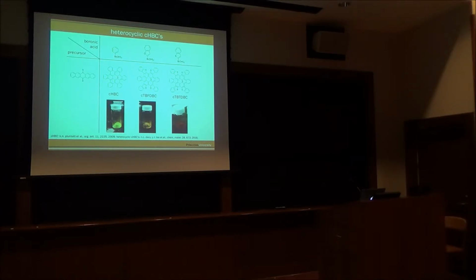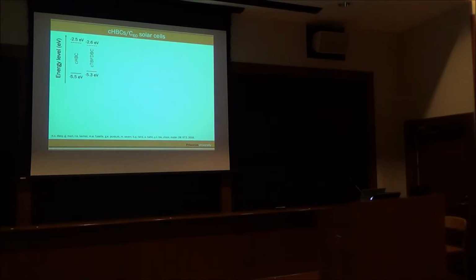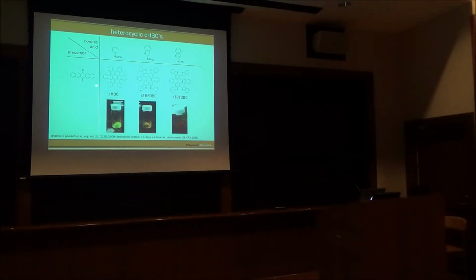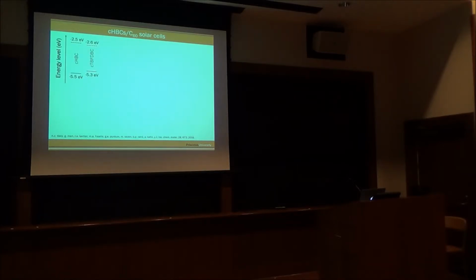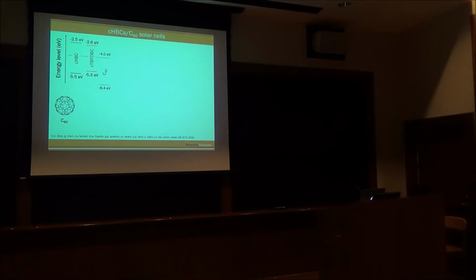So now that we have this, we can make a solar cell. These are the energy levels associated with these compounds. So this is the parent compound, CHBC. And then I'm going to show you work that's done on this benzofuran compound with the oxygen group. So this is the HOMO and the LUMO levels of the parent compound, and the HOMO and LUMO levels of this benzofuran compound. We need an acceptor, so we match it with C60. This is the commonly used acceptor. And so its chemical structure is shown here.